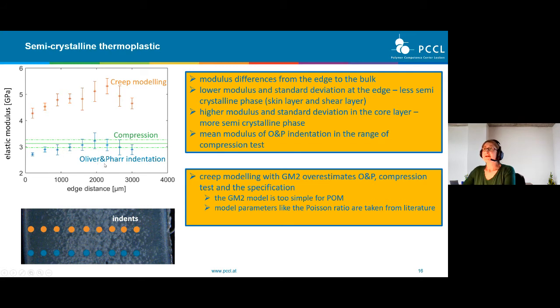Furthermore, the Oliver and Pharr indentation results fit to the results of the compression test. And the mean modulus of the Oliver and Pharr indentation is in the range of the compression test. But the creep modeling also has a lower modulus at the edge of the sample and a higher modulus at the center of the sample. But these measurements are overestimating compared to the Oliver and Pharr, the compression test, and also the specification. So we think that this GM2 model is too simple for the complex POM structure.